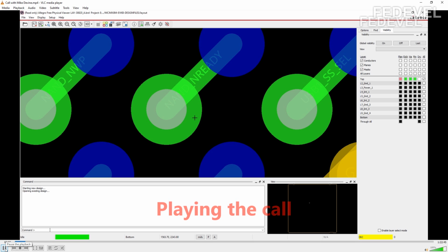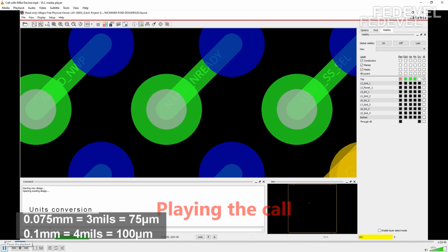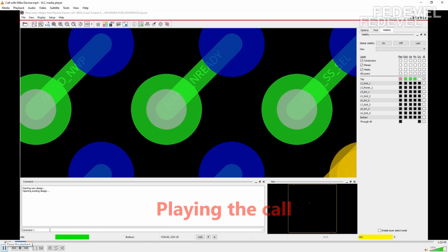We run with 3 mil. Obviously, yeah, 4 mil would be better. Gives you a little bit more annular ring, so that would take up any slight deflection of the through via. But we certainly manufacture here using a 3 mil ring, and it's quite common, to be honest.